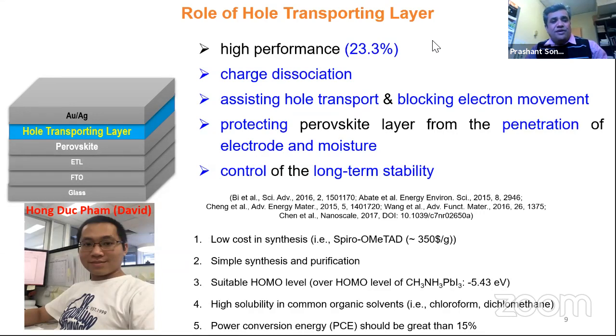So what is the role of the hole transporting layer? First of all, the hole transporting layer not only protects your perovskite layer underneath, but it also assists hole transport and blocks electron movement depending on the HOMO value. It really helps a lot to dissociate the charges which are forming in perovskite, because unless we have a hole transporting layer, efficiency can be limited to maybe 14 or 15%. So in order to push this efficiency up and to collect most of the charge carriers, we should have this hole transporting as well as electron transporting layer. Then it protects the perovskite layer, which is good in terms of enhancement of stability against moisture and so on.